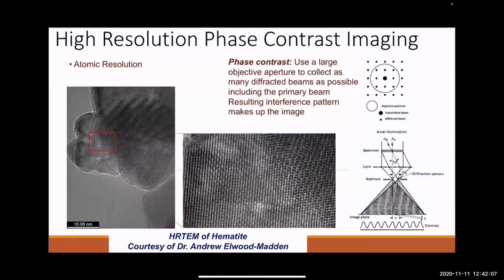So you can get positions of atoms. You can look for defects, for example, in a crystal. You can get lattice parameters, the spacing of atoms, things like that. I should mention that this is a little more complicated, because depending on your focus, just a little subtle change in the focus can make the bright spots go dark, or vice versa. And so you really don't know what the actual atomic position is sometimes. And sometimes that's okay. That's good enough to see defects.